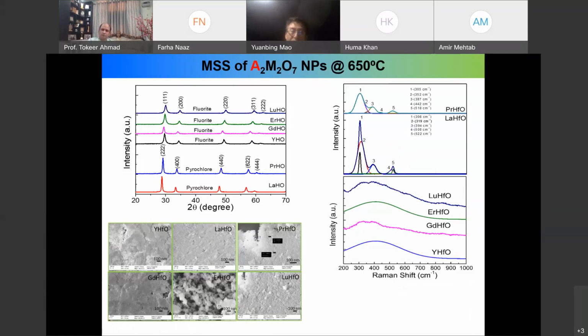And we can see that, even though these nanoparticles were synthesized at 650 only, all of them actually show the crystal structure. So that definitely shows that the molten salt synthesis can lower the synthesis temperature quite a lot. And for the particles synthesized at 650, we can take the Raman spectrum, and we can see for these two, we already got the pyrochlore crystal structure. And then from the SEM images, we can see the nanoparticles.